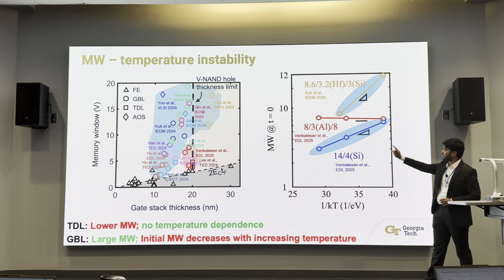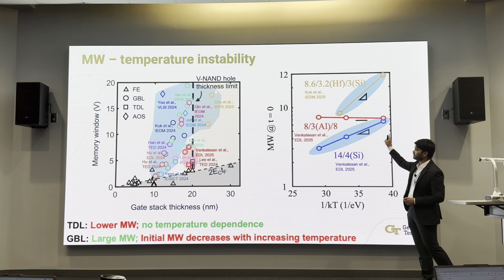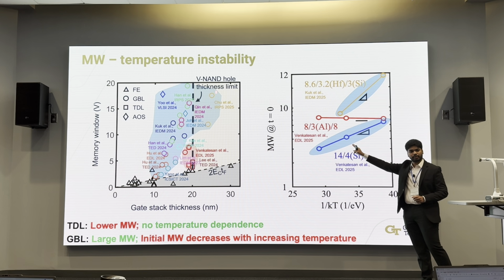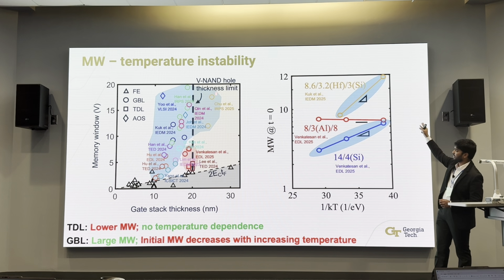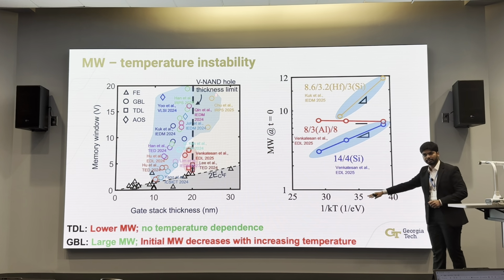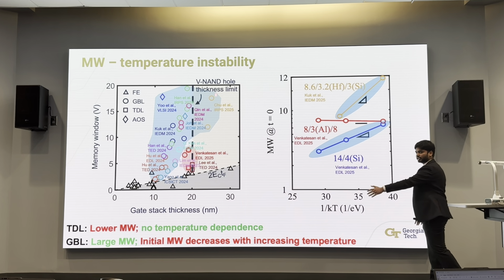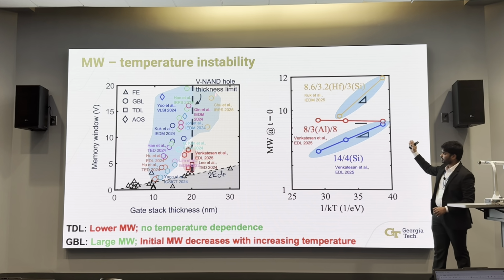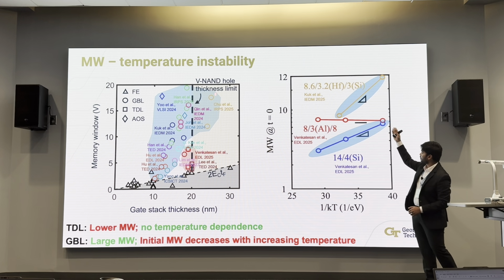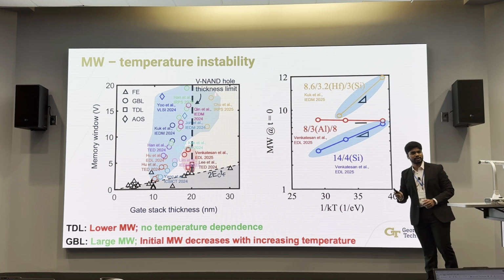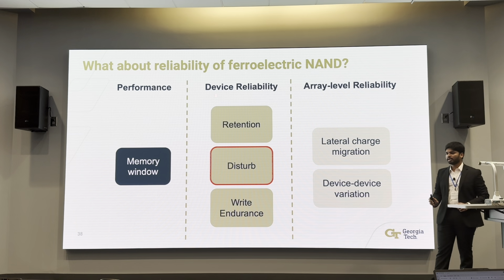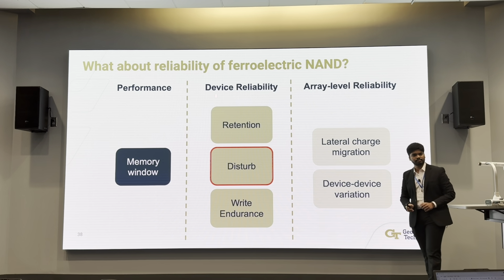But at the same time, the tunnel dielectric layer devices have a temperature invariant initial memory window, while the gate blocking layer devices, as you can see here, temperature is plotted as 1 by kT. So when you move to the left, it's increasing temperature. So as you increase the temperature, the memory window of the gate blocking layer devices continues to decrease, which is undesirable.